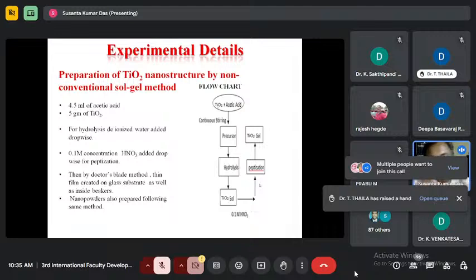So we started to do this type of experiment, starting from micron size powder. We went for making it nano dimensional powder. One method was the grinding method. Then another method was the sol-gel method that we did. But dissolving oxide in any solvent was a challenging task. We tried different things and we got this. This flow chart is showing that.